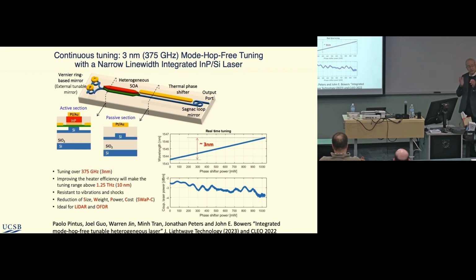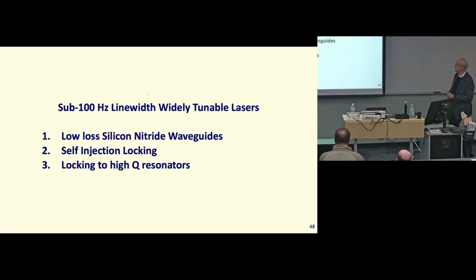Now these don't tune continuously very far. If you go very far, you get a mode hop of that cavity. The main design consideration, if you want maximum continuous tunability, is to make the whole cavity short. Shortening this up is what matters. The biggest we've seen is about 375 gigahertz, which is not a very good number. If you have an external grating-coupled tunable laser, you're used to something much larger, but that's because as you tune that external grating, the number of wavelengths in the cavity doesn't change. But at any rate, that's what it is.